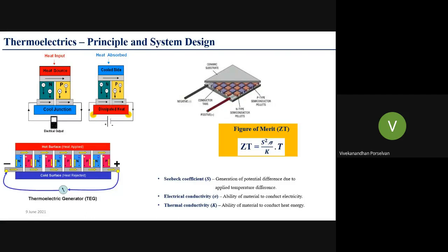So to have a higher conversion ability in the thermoelectric material, we should have a higher ZT. The ZT is a unitless number. The higher the number, the greater the conversion ability of this system. Thereby we can understand that in order to get a higher ZT, we should have a higher Seebeck coefficient and a higher electrical conductivity, which leads to a higher power factor, S squared sigma, and the thermal conductivity must be very, very low.